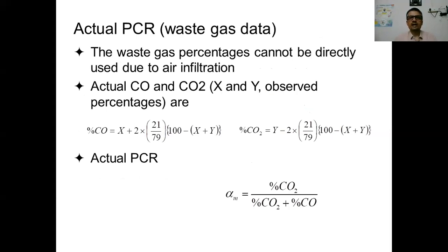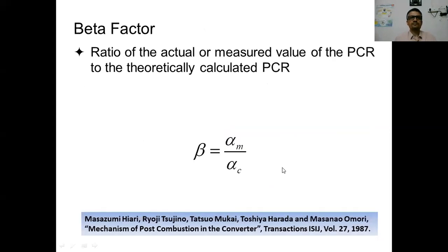So the waste gas percentage cannot be directly used, because the waste gas percentage is measured behind a cooling stack, which also contains some nitrogen because of the entrainment of air at the converter mouth. So it cannot be used directly for the calculation of the actual post-combustion ratio at the mouth of the converter. We have to subtract the contribution coming from the entrainment while it travels from the mouth to the cooling stack, and based upon that we have calculated the actual post-combustion ratio. And the ratio of the actual measured value of the post-combustion ratio to the theoretical post-combustion ratio is called beta.